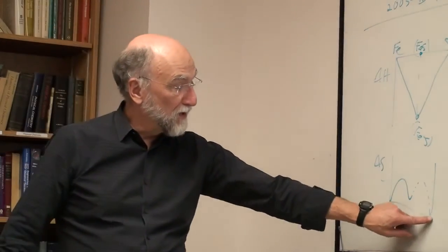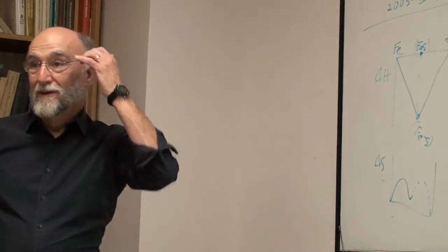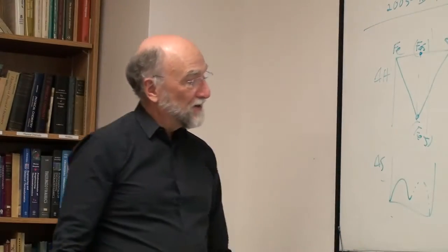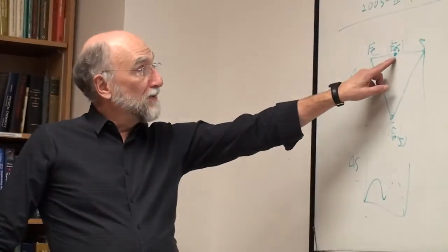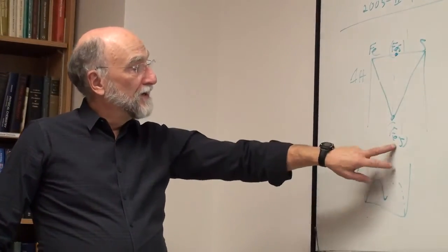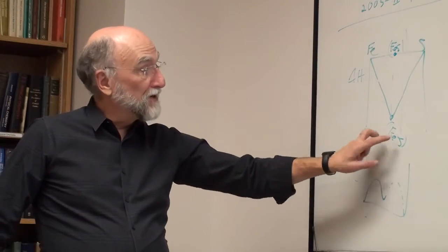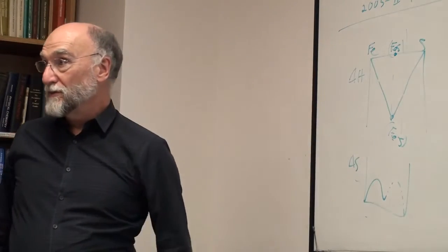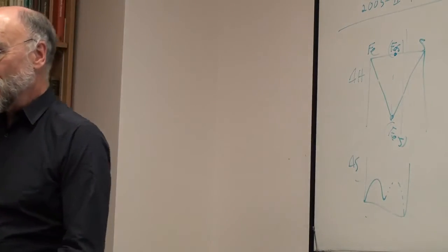To get over here, then it becomes more complicated because pure sulfur liquid is more complex, but at least up to say here you can treat it this way. So it's a typical case. You would treat it as a one sublattice model of iron and sulfur, but with a large amount of short-range ordering, meaning the iron and sulfur tend to form nearest neighbor pairs very strongly. Pure liquid FeS is almost entirely, first nearest neighbors would be 99% iron-sulfur. Very unlikely you're going to have two irons or two sulfurs next to each other because of the charge separation. The charge tends to localize on the sulfur to form sulfur ions.